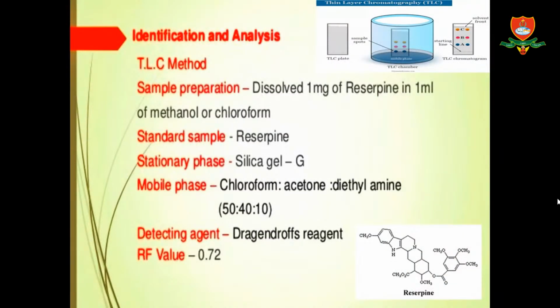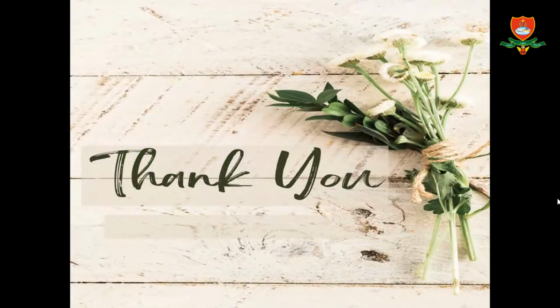So we identified and analyzed it by the TLC method. So here we took the sample by dissolving 1 milligram of reserpine in 1 ml of methanol or chloroform. So we took the standard sample as reserpine and the mobile phase as chloroform, acetone and diethylamine in the ratio of 50:40:10. And we took the detecting agent as Dragendorff's reagent and we got the Rf value as 0.72. Thank you, ma'am.